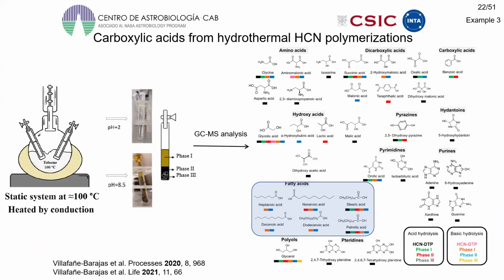Additionally, we explored other alkaline hydrothermal conditions of hydrogen cyanide polymerization, but in this case in the presence of minerals, and again we analyzed the reaction products by GC-MS after several hydrolysis conditions. We identified several monocarboxylic acids with more than 6 carbon atoms. That is, we detected fatty acids. Again, the hydrolysis conditions have significant effects on the analytical results of the samples.